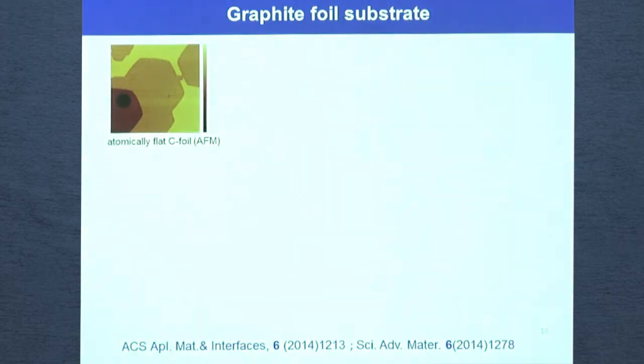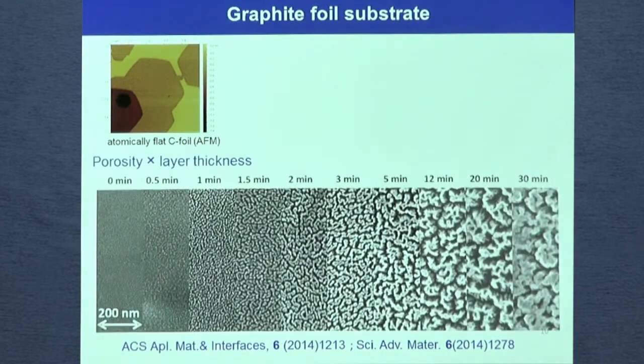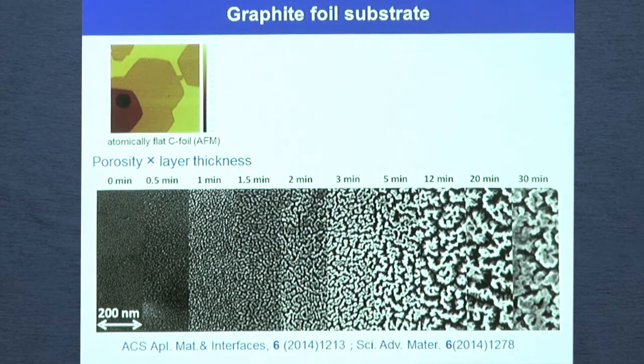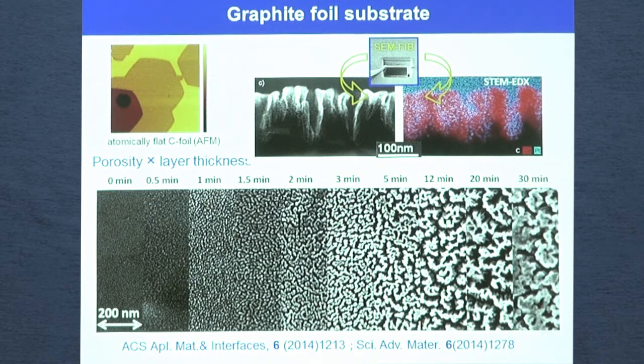Well, okay, and now how can we achieve porosity. The example is here. If we take atomically flat graphite foil, it means really very, very flat, and we coat this foil with different thicknesses of platinum or cerium oxide, you can see that we are creating a very porous structure. It is not flat and it's not compact. And the porosity depends on the deposition rate and also on the thickness. Thickness here means the deposition time. And if we check the cross view of the layer, we can see that in fact we are etching deep nanochannels inside the carbon substrate. So really we are etching holes, which are coated with catalyst.